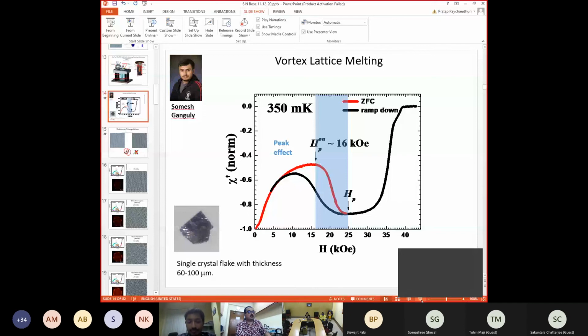Yes, so we did not get it for two reasons. One reason is that for a BKT transition, you need a two-dimensional system. You consider the vortex lattice to be two-dimensional when you can consider each vortex almost as a point object, and they are on a plane. But if the vortex is long and inside it has this third degree of freedom of bending, then it is no longer a two-dimensional system. It has activity in the third dimension, which makes it not a system in which you should see BKT. Second thing is that there was a considerable amount of pinning.